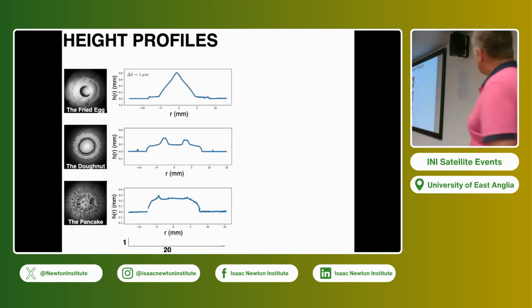Okay. So I will not discuss too much about that, but we did some work about understanding the different shapes that you obtain at the end. We will not discuss that today, but basically we could understand quantitatively the thickness of that by using the 1D model of ice formation. So basically if you compare the thickness of this ice layer with the square root of Dt, taking the time that you observe before the retraction, it works quite well. And again, if you compare the solidification speed with the retraction velocity, you can separate these two regimes very easily.